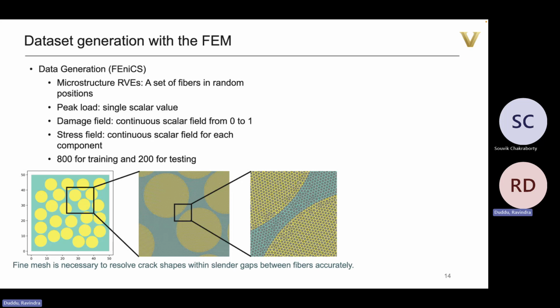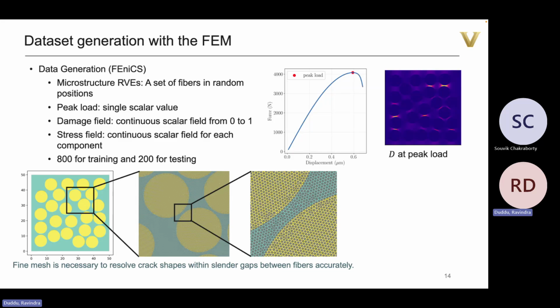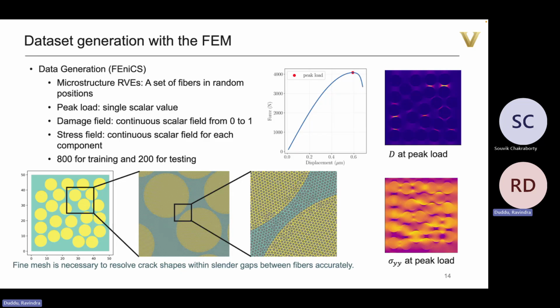Okay, so we still have parallel computing. We have a very good server, so we could run it in embarrassingly parallel fashion. And once we do each of those simulations, we get a force displacement curve. We can capture that peak load up there. And then at the point where the peak load is, we can also get the distribution of damage in the microstructure, like an image, correct? And then we can also get the image of the stress field at this point, okay?